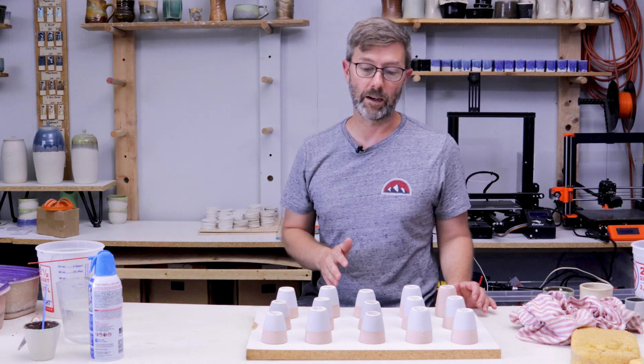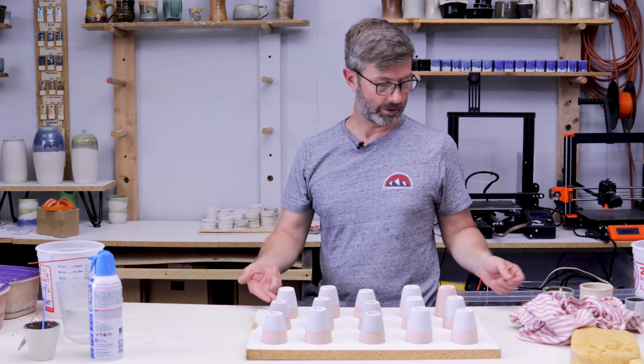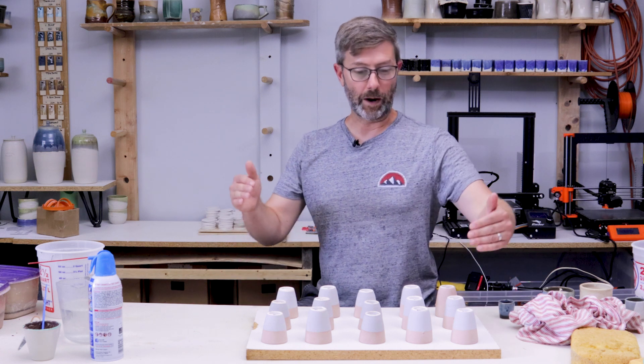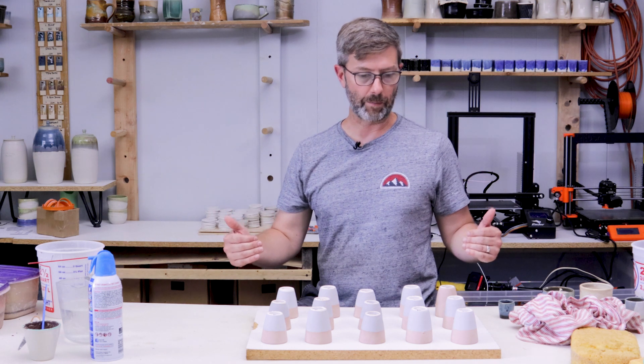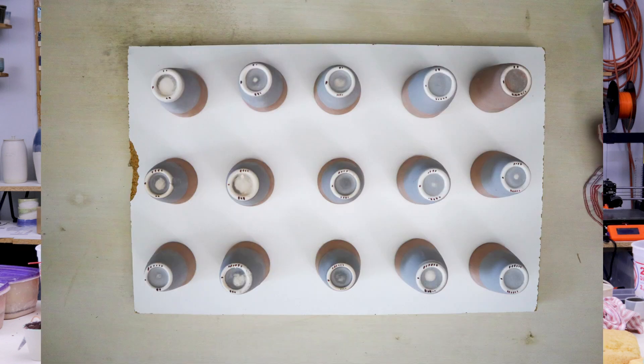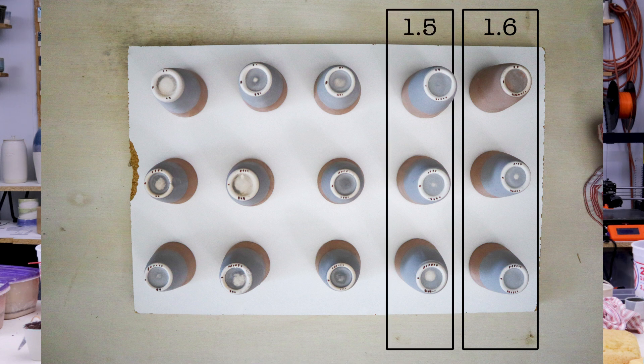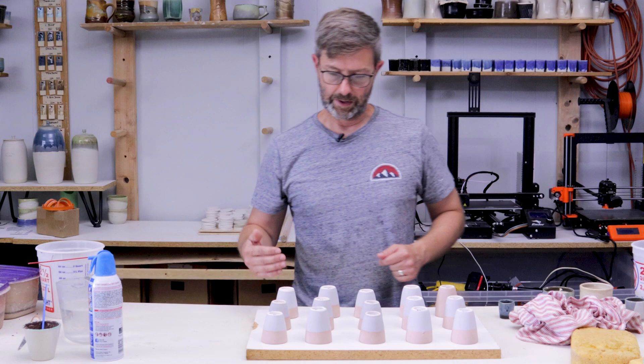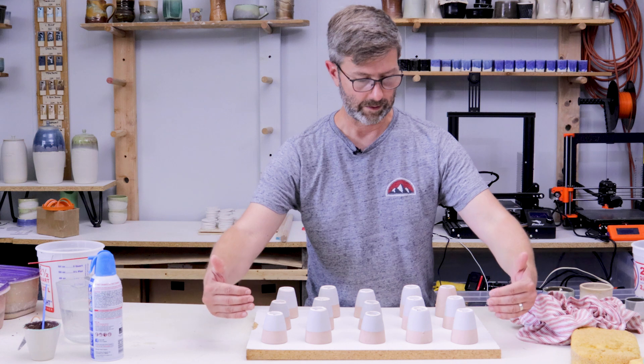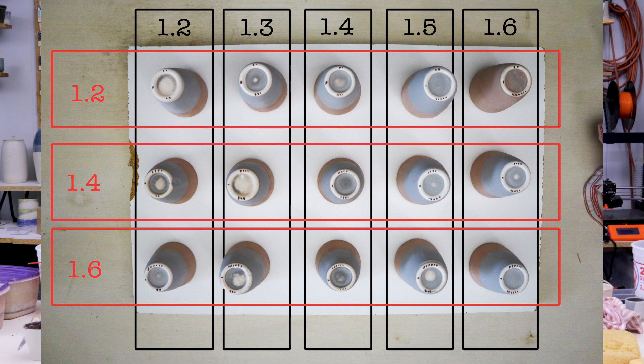I knew the base glaze was a glossy black, and then the top cover glaze was this — I'm going to call it 'infinity' or 'universe juice' from Kung Fu Panda. What I have is a grid: the base glaze of black runs across this row at specific gravities of 1.6, 1.5, 1.4, 1.3, and 1.2. The cover glaze runs down the rows at 1.6, 1.4, and 1.2.